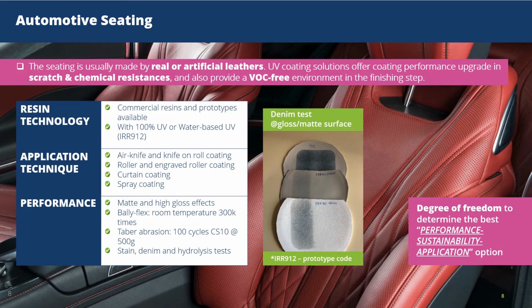Looking at the pictures of the denim test, IRR is a water-based solution that was coated on PVC substrate. It was formulated as a high gloss system and as a matte finish. And as you can see, the UV-curable solution offers excellent stain resistance in both the matte and the high gloss finishes. Additionally, IRR 912 survives 300,000 flex tests on the Bally test.